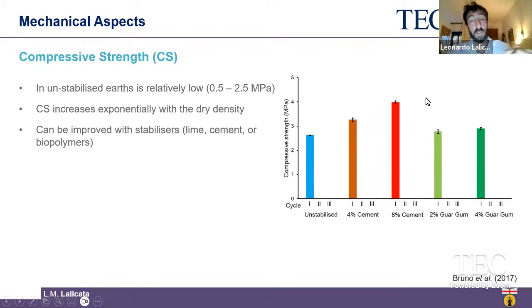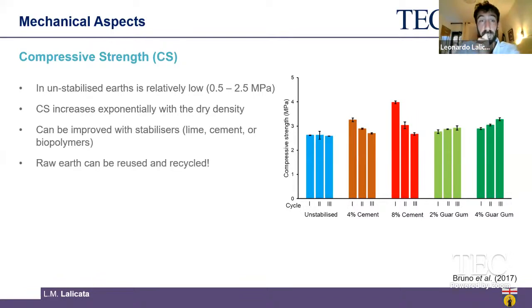But also regarding the effect of recycling this material, because earth, you know, you could virtually reuse a number of times. So in this study, made by Bruno et al., after testing the samples, they crushed them and built novel samples to test the influence of eventual degradation of the compressive strength over different cycles. And what they found is that the standard unstabilized earth did not reduce its strength with the number of cycles, while on the contrary, for the earth stabilized with 4 or 8% of cement, you have a